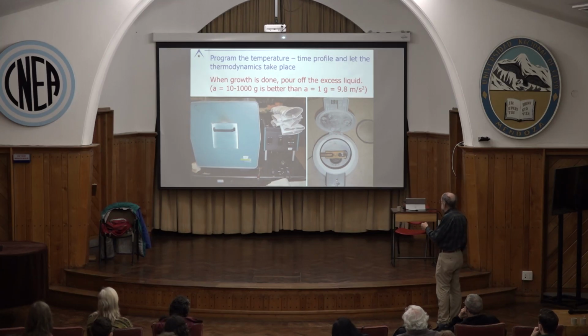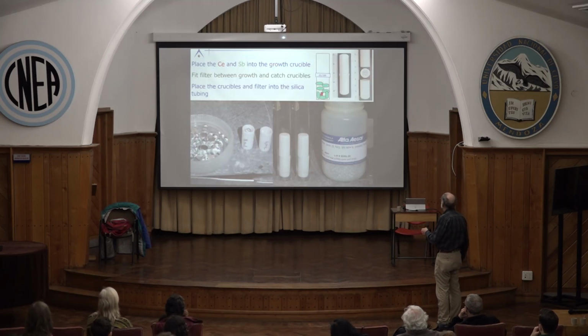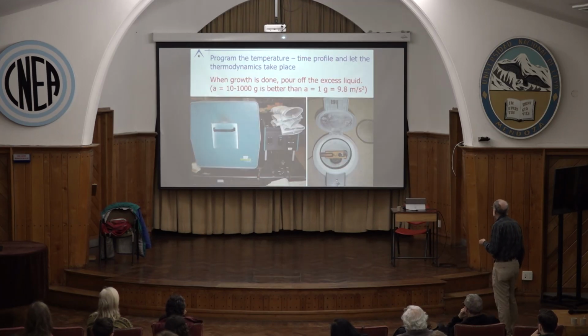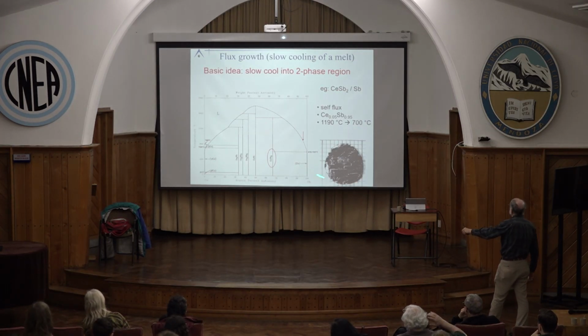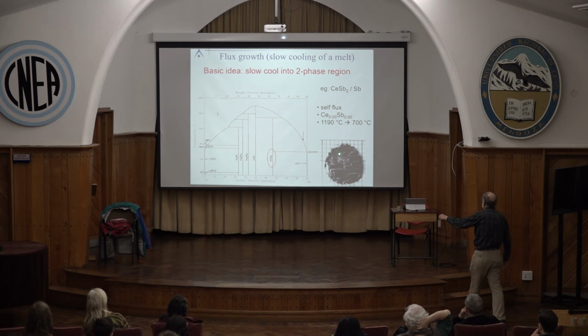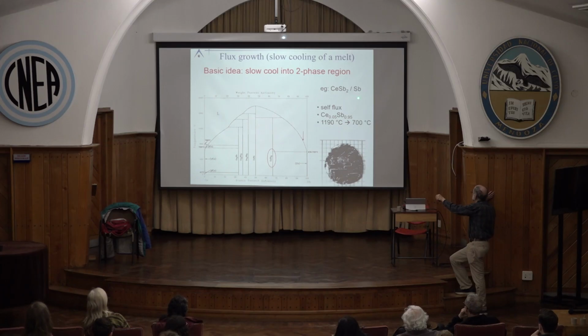So remember, we had this fritted crucible. So that means I'll have my crystals here and all the nice liquid there. And then it solidifies in. It's good. And as a result, you can end up with beautiful plate-like metallic micaceous cerium diantimonide. If I were to write this in my lab notebook, I would just say cerium diantimonide out of antimony, self-flux, 5% cerium, 95% antimony, 1190 to 700.